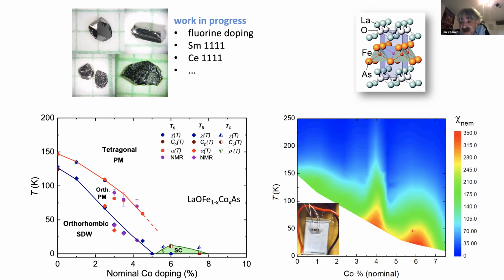So when there's a nematic susceptibility, which is purely electronic, starts to grow, at some point there will be kind of a critical temperature where the lattice starts to communicate with it. And then, it's not very surprising to find that it turns into, as I remember it, a first order structural transition from tetragonal to orthorhombic. Having said that,